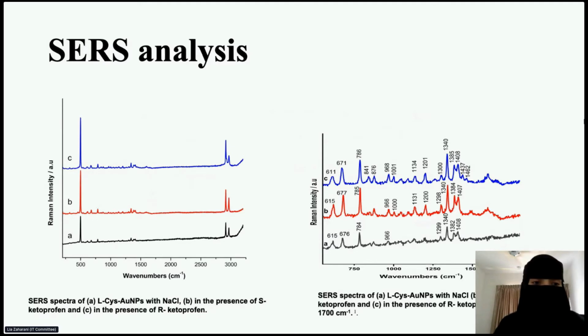So the spectrum of L-Cysteine gold nanoparticle, A, shows a huge peak. This peak corresponds to the S-S bond. It's known that most L-Cysteine tends to form an S-S bond by the collision of two L-Cysteine to form cystine. So this also shows that the L-Cysteine aggregates and is near the surface of the gold nanoparticle.